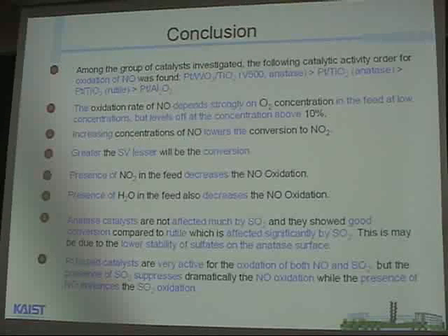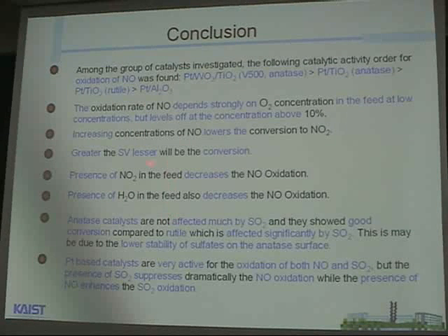These are the conclusions. To conclude all these things, this catalyst gives a higher conversion than the rest, and the oxidation rate depends on oxygen concentration, but it levels off at high concentration of oxygen. With increasing NO concentration, the NO2 decreases.